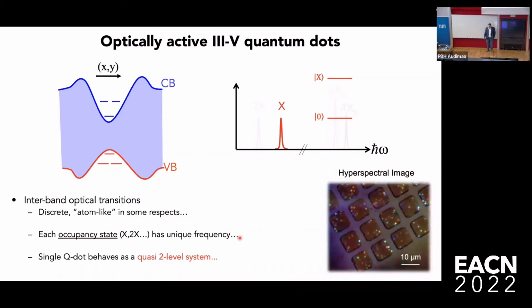There you see a typical device from our lab. Each one of these windows is 10 by 10 micrometers, and we've done a hyperspectral image, so you see these false color-coded quantum dots. We can find out where they are, and we can fabricate photonic structures around them and address them individually. Yeah, and this is what many people in the community are doing. So single dots really selected for site-selective nanofabrication. And I'll show you later on how we now, or many groups, place resonators, antennas, lenses very precisely around single quantum dots to allow them to be very, very efficient.